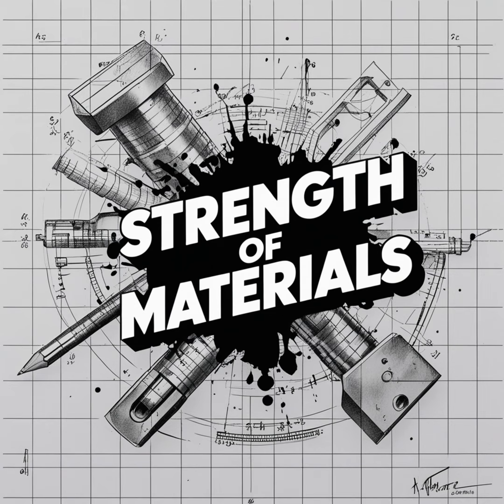Let's take case 1. High stress first, low stress second. You apply a massive violent cyclic load to a pristine part. Because the stress is so high, it easily initiates microscopic cracks at the surface of the metal. Okay, damage is done. Then you lower the load. Now you are applying a gentle low-stress cycle. But the cracks are already there. Precisely. That gentle low stress might never have been strong enough to initiate a crack on its own. But because the high stress already opened the door, the low stress is perfectly capable of propagating those existing microcracks.